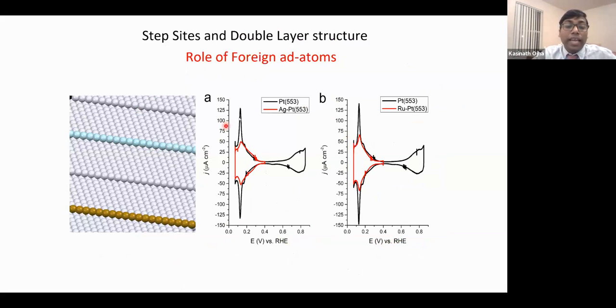So once we added silver atoms on these step sites, and another time we added ruthenium on the step sites, this is a very controlled deposition. Electrochemistry-wise, it's a very controlled deposition. From the electrochemical signals, you will be able to say how many atoms of silver or ruthenium you deposited and where exactly they were deposited. It's all very informative in the electrochemical signature.